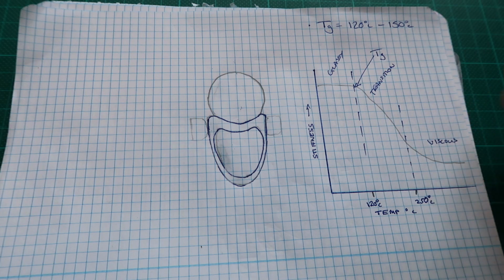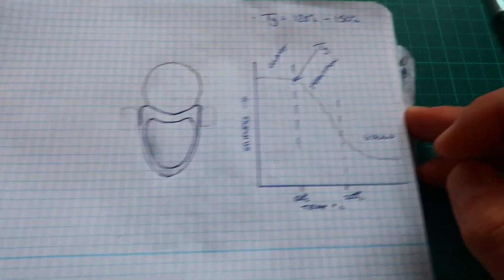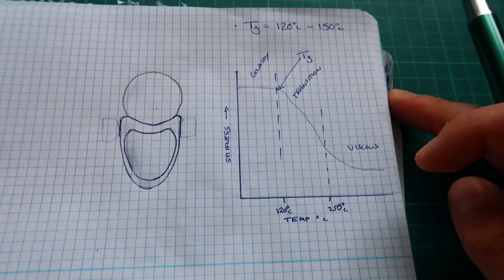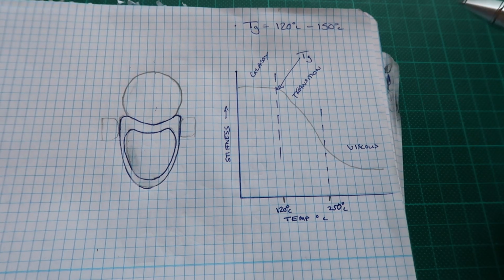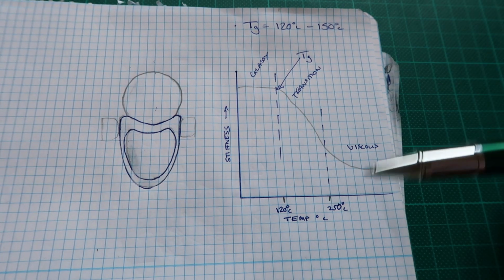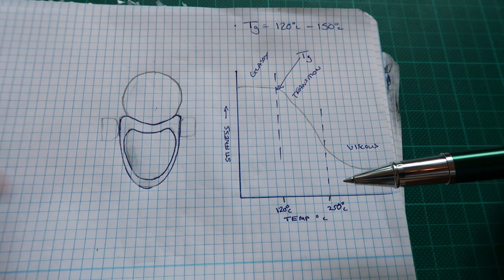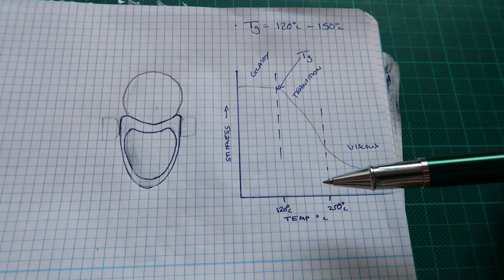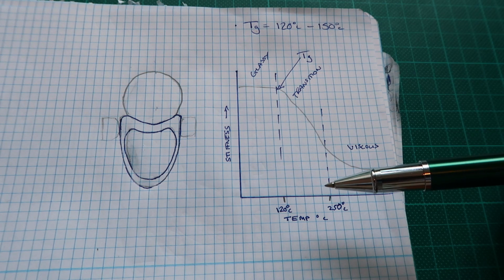Now, what do I mean by Tg temperature? Well, the Tg temperature, like I said, is the point at which the resin really starts to lose its stiffness. For most basic pre-preg resins that would be used in something like this, you're looking at around 120. With much higher end heat resistant resin, you can get up to about 150 or even 180, but they are quite expensive and probably not used so much in the bike industry.